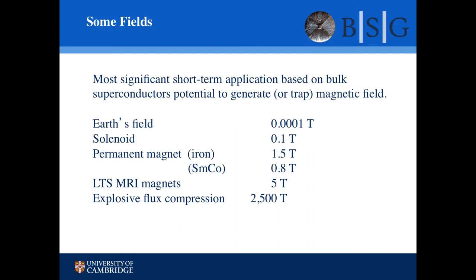Okay, so here are some fields. The Earth's magnetic field is about 0.1 of a millitesla, pretty small. A solenoid, so you wind a coil in the laboratory. If you're lucky, you can get to about 0.1 of a tesla. A permanent magnet, the best you can do practically is about 1.5 tesla. That's iron, but you have to make it in the form of a long, thin rod. That's how the Victorians used to make their magnet. Samarium cobalt, neodymium boron iron is around about 0.8 tesla.